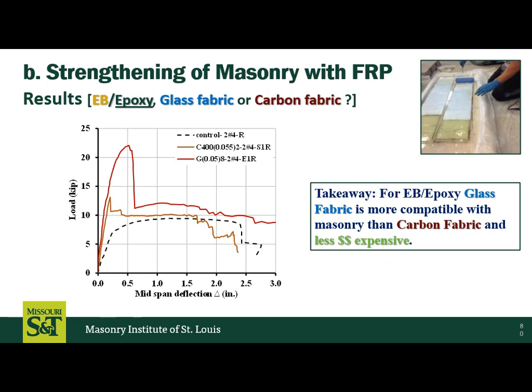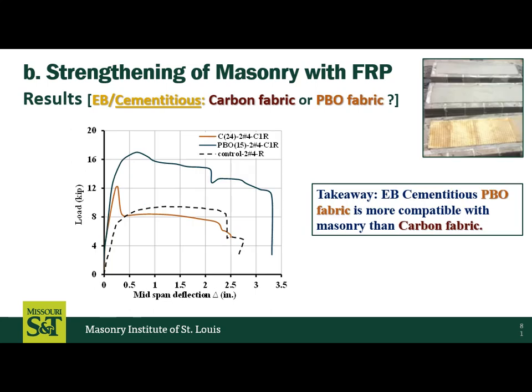I could pick a really, really hard, dense aggregate like a trap rock. And if I want to develop a high-strength concrete, maybe 15 KSI or something, that hard, dense aggregate that's stronger than a dolomitic limestone, you would think, oh, I can develop higher strength concrete. You can't. The materials aren't as compatible. It creates more stress concentrations, and hence the lower strength aggregate is actually better than the higher strength. And it's kind of a similar takeaway here, where the glass is better than the carbon, as you can see here. And then for the externally bonded, using this PBO fabric that you can see here, again, that is more effective with the PBO rather than a carbon sheet.